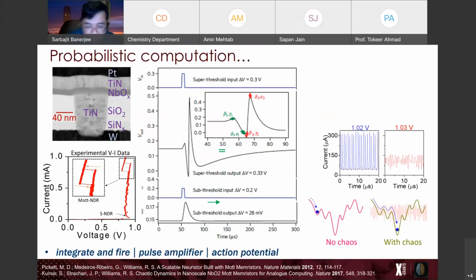Here's some work by Stan Williams, a couple of papers in Nature in 2012 and 2017, that demonstrates this with a compound called niobium oxide. Niobium oxide undergoes an insulator-to-metal transition at above 900 degrees C, and using that transition, the switching of the material from an insulator to a metal, you can get all kinds of neuron-like functions. You can see here this idea of a sub-threshold input that is filtered out, and a super-threshold input that results in an amplification, an action potential, and then what you can start building from the structure.